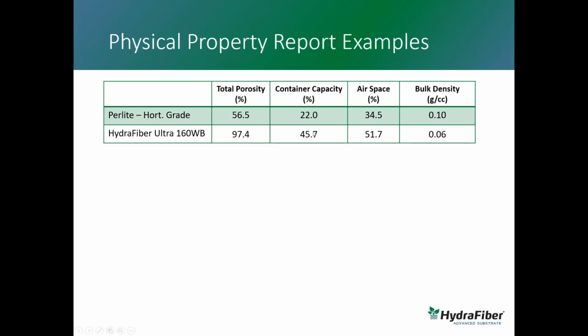Now, when we look at the water holding capacity, Perlite is only 22%, whereas Hydra Fiber has about double the container capacity of Perlite, okay? Perlite is being used in the substrate as an aggregate to add air, so it's no problem in this given context that it has such low water holding capacity. But it's very interesting to see that we have such high water holding capacity in the Hydra Fiber. And that's directly related to the fact that we have very high total porosity.